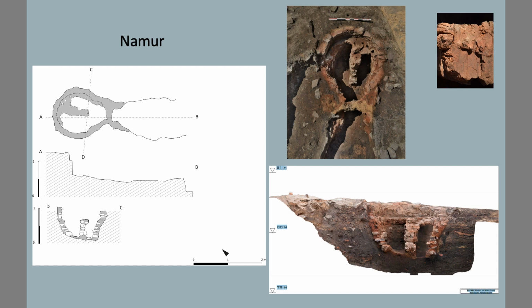The floor was placed on planks of wood that left traces in the fired clay. The floor is also pierced with at least 8 peripheral vent holes. Above the floor, 2 ranks of stone were preserved. They slightly retracted, initiating the covering of the firing chamber by a vault. Given the thickness of the rubefaction, from 15 to 30 centimeters, it is clear that this kiln was used several times. The first analysis of the material placed in the kiln reveals that the walls were made between the first quarter of the 6th century and probably the 7th century.